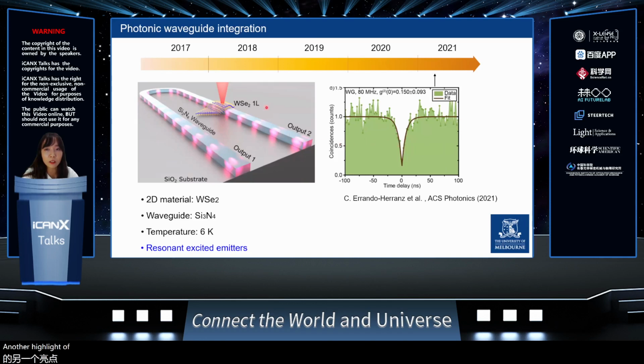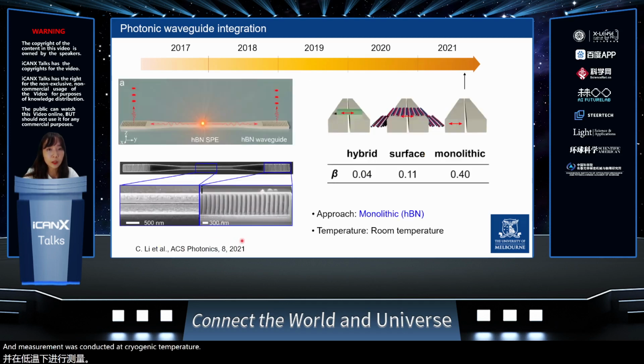Another highlight of last year is the experimental work by Errando-Herranz and the team. In this case, single photon emitters in WSe2 were resonantly excited and coupled to a waveguide, and the measurement was conducted at cryogenic temperature. And last year, in August, we also successfully demonstrated the monolithic system for the first time. In this case, the waveguide is now made of hBN crystal and contains hBN single photon emitters. Because we are using a monolithic approach, we can simplify the fabrication process by eliminating the transfer step.